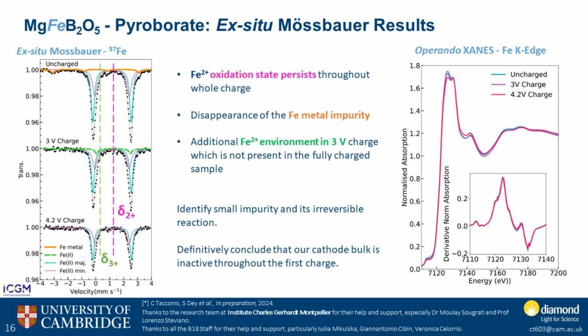And we also did some operando XANES, where we were looking at the iron K-edge as well. Here, typically with battery materials, if you were studying the XANES, you would expect a shift of this pre-edge position with oxidation, and it's not happening, or reduction, and it's not happening. So we know that there is no iron redox and that likely our cathode phase is not demagnesiating. So we didn't want to stop here. We wanted to try and figure out what was actually going on inside the battery to inform in future what could be important to take care of while making these materials.